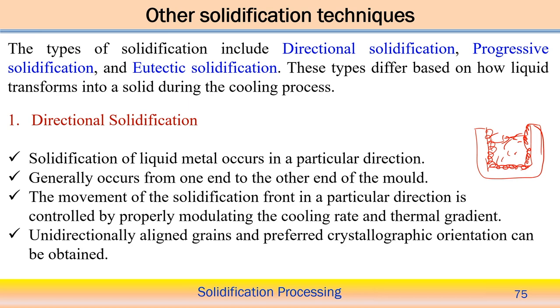Therefore, the movement of the solidified front in a particular direction can be controlled by properly modulating the cooling rate and thermal gradient. We know that G and R, the temperature gradient and the growth rate, are usually the two solidification parameters, and by combining these two parameters we can decide the solidification mode, and the cooling rate we can also estimate. So by controlling these two, it is possible to move the solidification front in one particular direction.